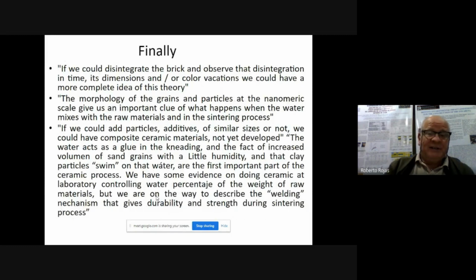The morphology of the grains and particles at the nanometric scale gives us an important clue of what happens when the water mixes with the raw materials and in the sintering process. If we could add particles, additives, of similar sizes or not, we could have composite ceramic materials not yet developed. The water acts as a glue in the kneading, and the increased volume of sand grains with a little humidity, and clay particles swimming in that water, are the first important part of the ceramic process. We have some evidence from doing ceramic at the laboratory, controlling water percentage of the weight of raw materials, but we are on the way to describe the welding mechanism that gives durability and strength during the sintering process.